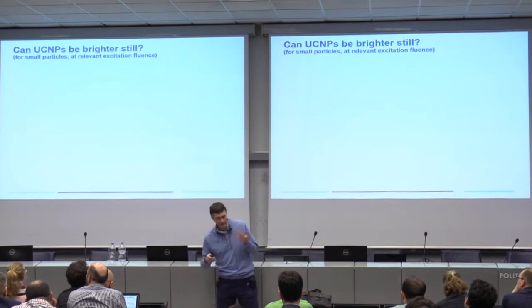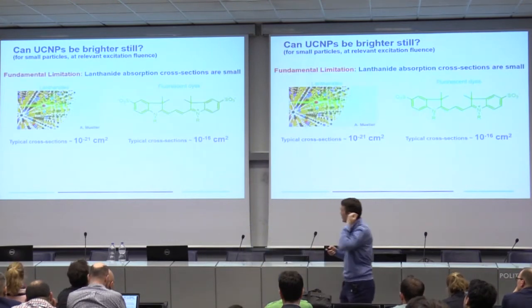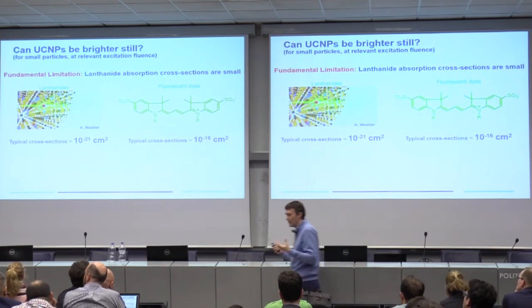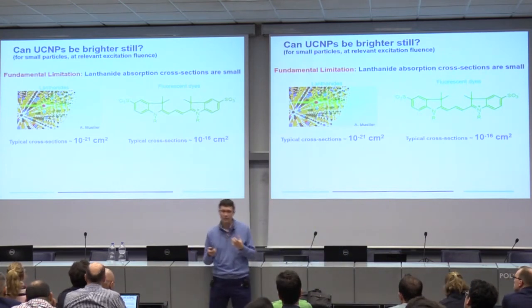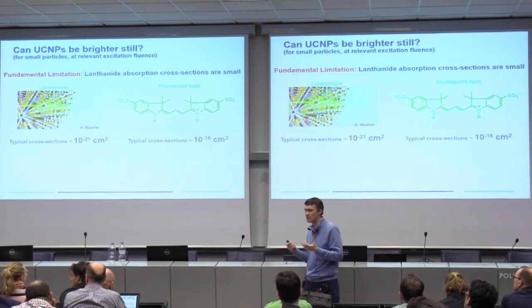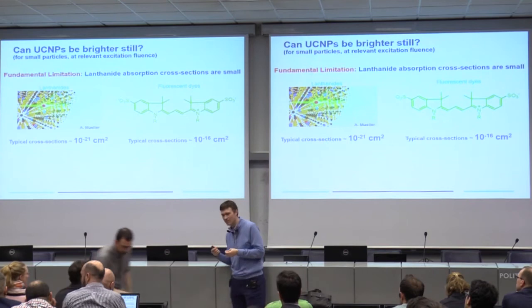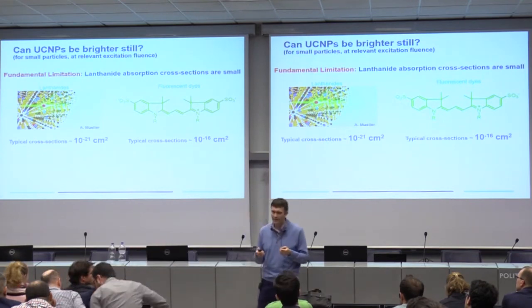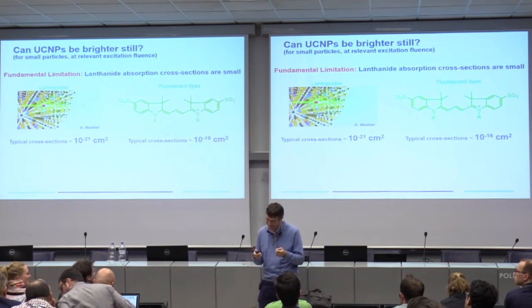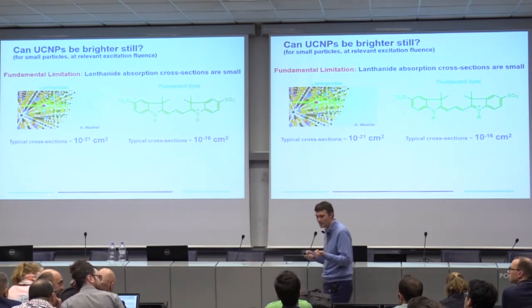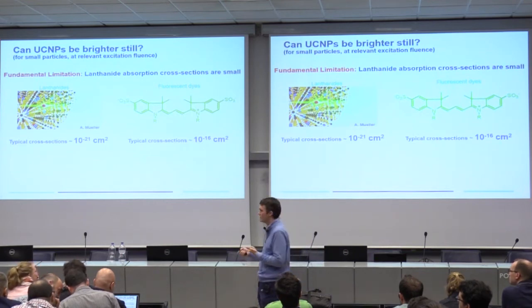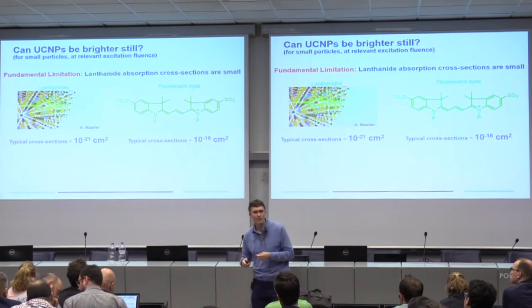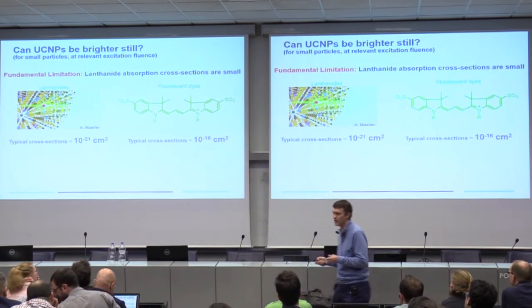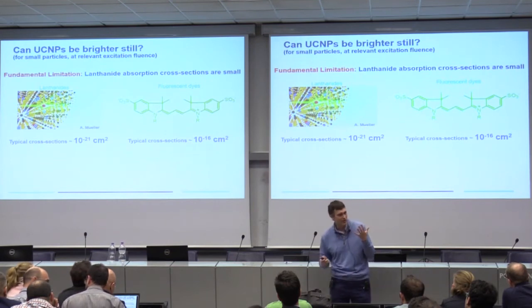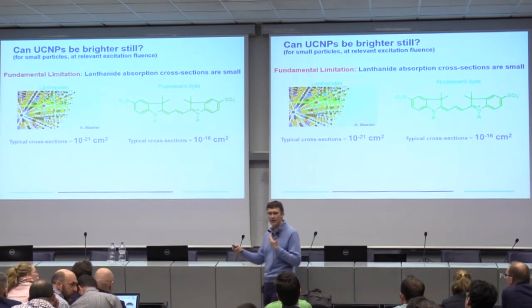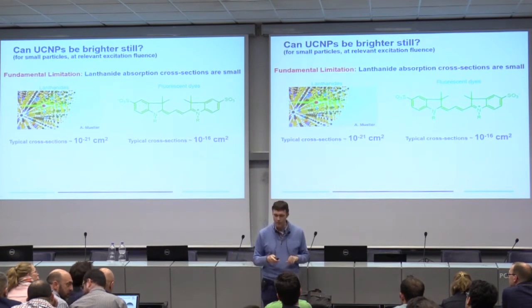And so this led us to think about something a little bit more fundamental within the particles. Even if you have an upconverter and you load it up with as many lanthanides as possible, what's the limitation to how bright this particle is? It turns out the fundamental limitation is the absorption cross-section of these lanthanides. The absorption cross-section of a lanthanide is really small, 10 to the minus 21 square centimeters. Meanwhile, the absorption cross-section of a fluorescent dye is much larger, 5 orders of magnitude larger, 10 to the minus 16. And so maybe there's a way to combine these two to improve your upconverter.